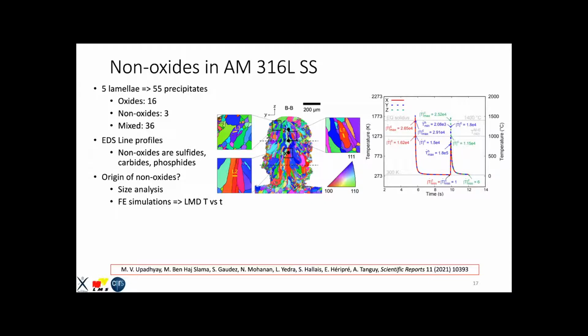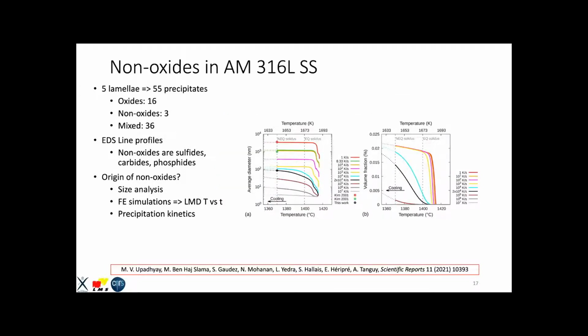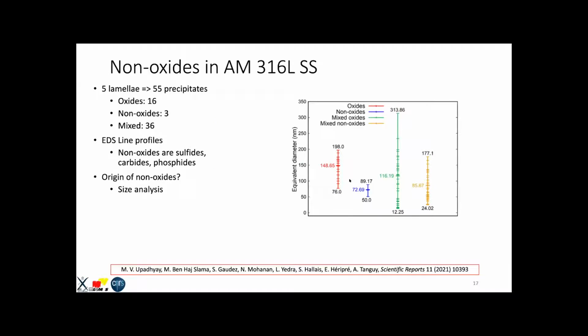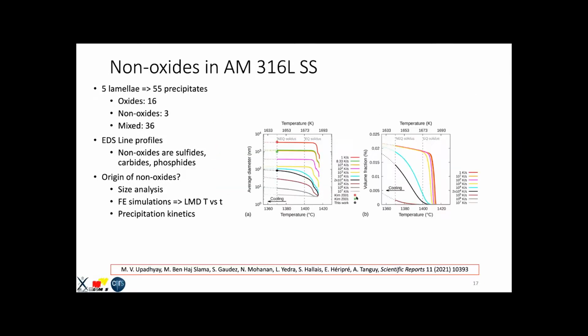Now, the next step was to do finite element simulations to understand the temperature versus time relationship along this microstructure as it's being built. So Nikhil did some simulations to find these temperature versus time curves at these points X, Y, and Z in our simulated geometry. And we found an average temperature rate of 20,000 Kelvin per second. We took all this information of the size and the temperature versus time curve and put it into a precipitation kinetics model, where we said that at 2 × 10⁴ Kelvin per second, which is this black curve, we should have a size of non-oxide precipitates of the value that we saw here, which is this one.